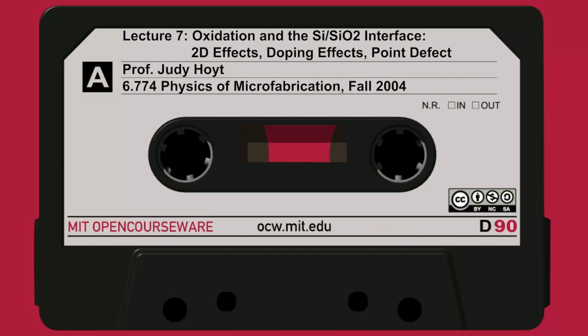What's the difference? Maybe you'd see a little difference in wafer curvature. That's a way you could measure it. All right, that's fine. Now you go to the next step in your process. Say I want to grow another oxide underneath these 2 at 800 degrees. Now, if I hadn't said anything about stress, Deal-Grove would say, I have 1,000 angstrom oxides here, 1,000 here. I put them both in the furnace. You just use Deal-Grove, and you would get the exact same thickness on both wafers. Deal-Grove doesn't tell you anything having to do with the history of how you grew the prior oxide layer. It just depends on, remember, just the T sub I, the initial thickness. It cares nothing about what temperature that oxide was grown at.